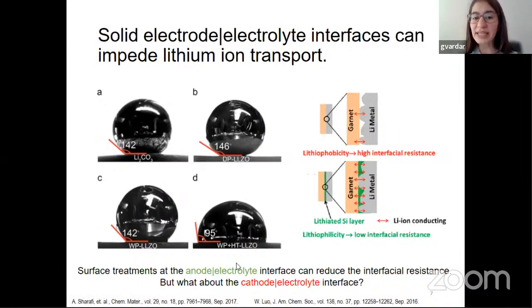The interface between lithium and these solid electrolytes, a lot of work has been done there. And you can see in this one, for example, that this droplet here is the lithium. And then here at the bottom, this surface is a solid electrolyte surface. We were able to compatibilize these two materials and have them contact each other easily.